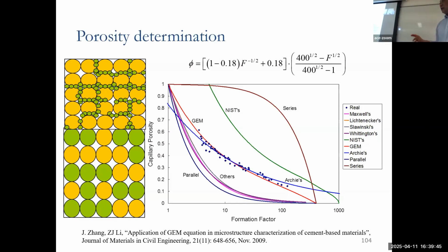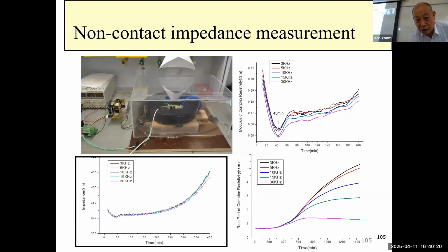My third student used this technique to measure the porosity inside the concrete, the total porosity. That's the formula he developed, and F is a factor we call the formation factor. That is the ratio of the resistivity of the concrete to the resistivity of the solution at that time. The prediction is very accurate. You can see the red curve is our prediction, and all the dots are experimental results from many different research studies.